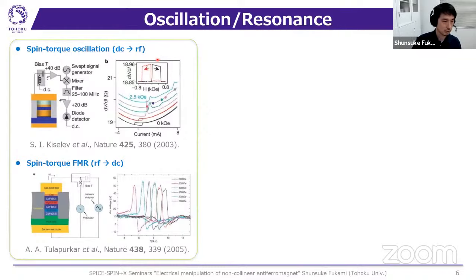Okay, and the third example is oscillation or resonance. Again, the Cornell team demonstrated that the DC current can induce stationary oscillations and emit RF signals at a specific magnetic field. And also the inverse process was observed by the Osaka University team: they applied an RF current, and then through the ferromagnetic resonance, a DC signal was observed at the specific frequency, at the specific magnetic field.